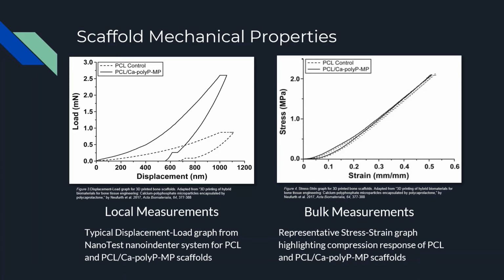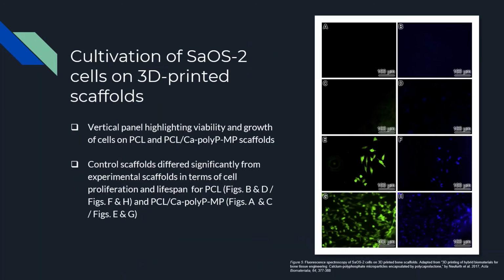The PCl and PCl calcium poly-P scaffolds had compressive moduli near 4.0 megapascals, again determined by the slope of the stress-strain graph, and a maximum strain of around 30% when subjected to compression. In order to assess biocompatibility, the scaffolds were subjected to in vitro growth studies of SAOS-2 cells. Controls for both scaffolds showed no growth during the 3-day incubation period.